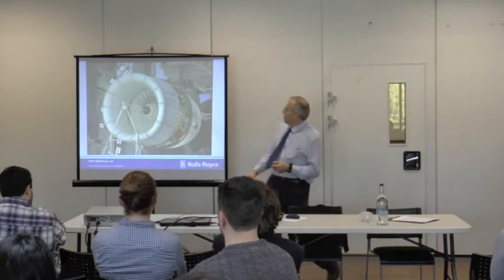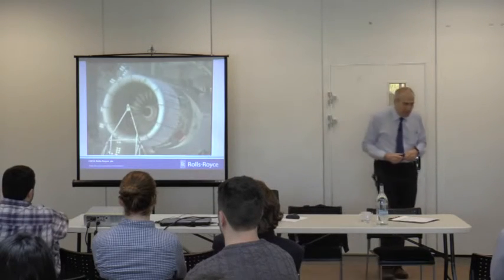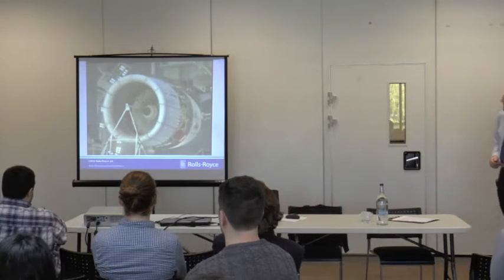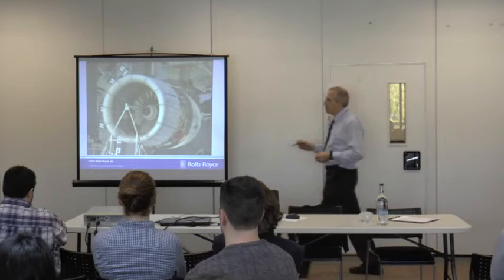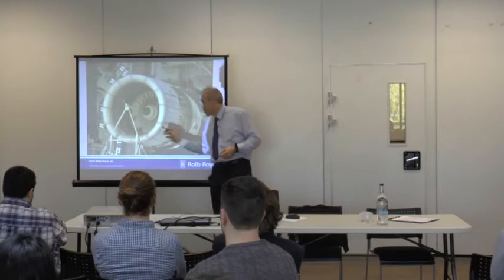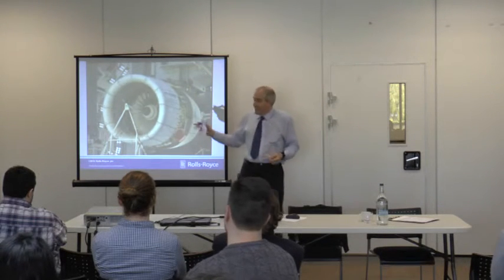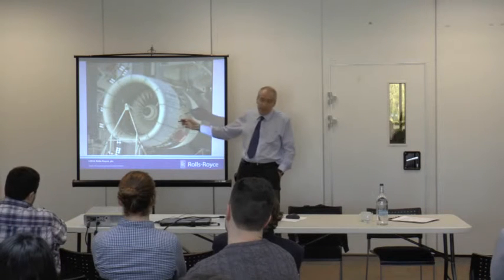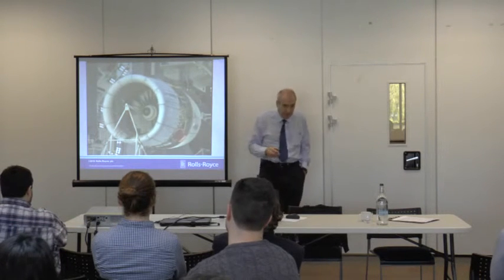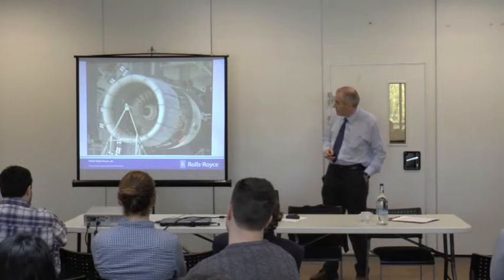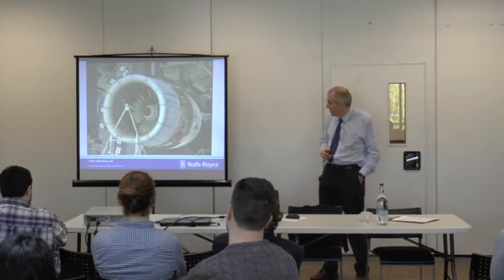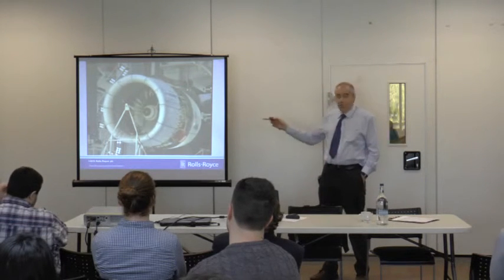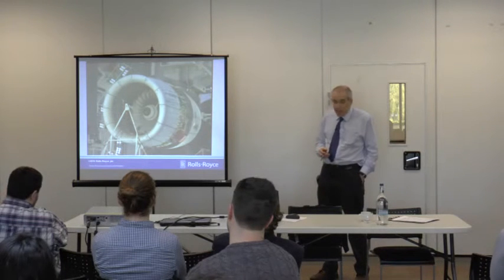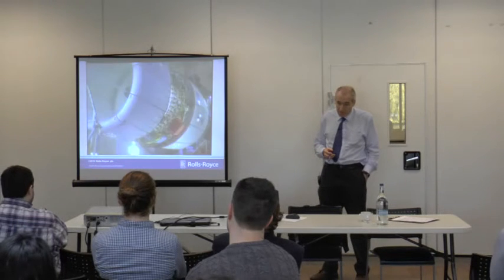Right, oh, watch this, there you go. So that's 20 million quid, please, to do that test, give or take. Final test that we do, fan blade off, and what we have to demonstrate is that that blade is safely contained within the engine. So the total kinetic energy and the energy density, where that impacts on the case, same order of magnitude as tungsten long rod penetrators they use to destroy tanks in the military. We haven't got 70 tons of armour, we've got a few hundred kilos, which makes life quite challenging for us.